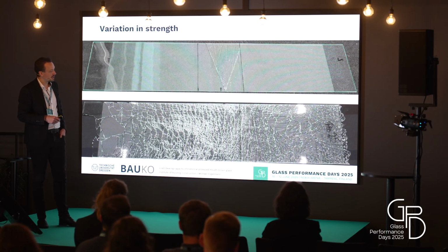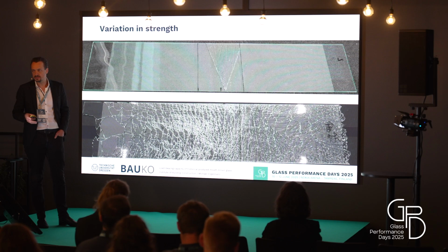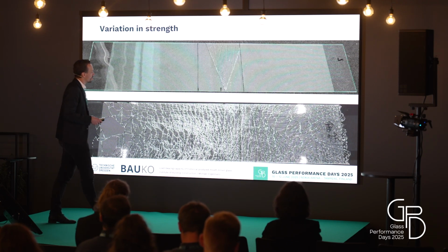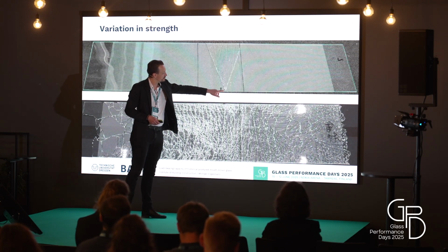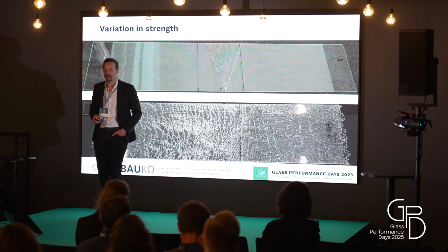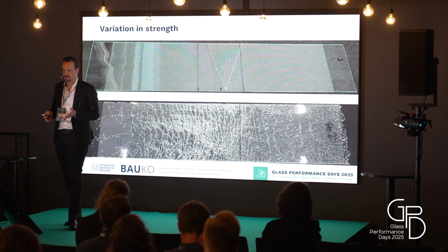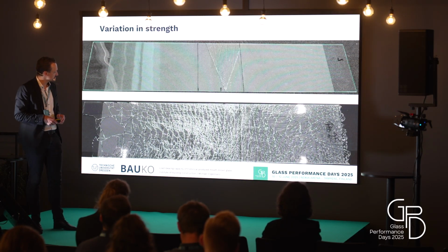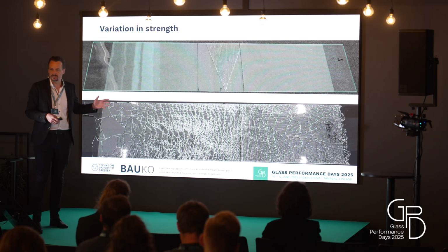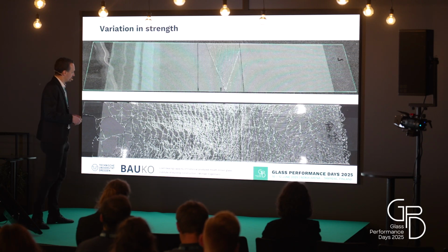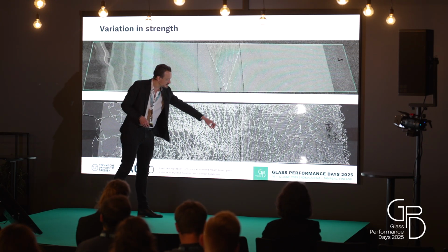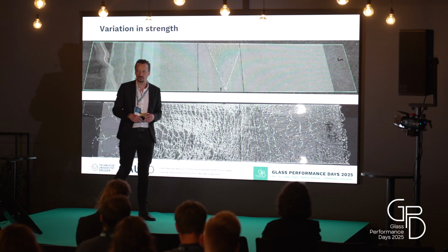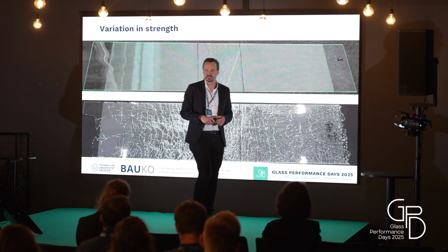On the top, we have a sample for the float glass, and I think we see what we expected. This is a float glass sample. It broke right here at the edge with a typical fracture pattern. On the bottom, this is a sample of a tempered glass. You see, of course, this is not a traditional fracture pattern test. It's after mechanical testing. So, of course, we have really small fragments right here in the center where we have the largest load and the largest mechanical energy.